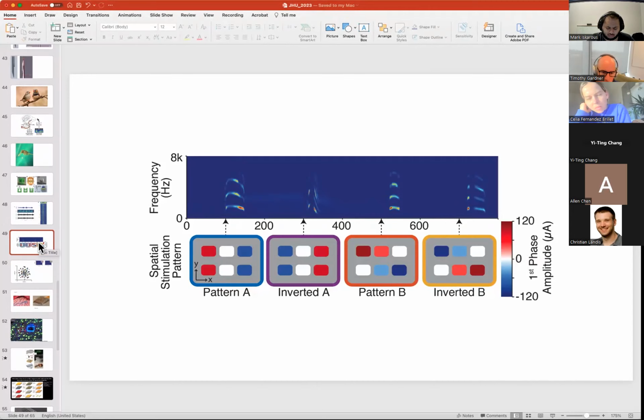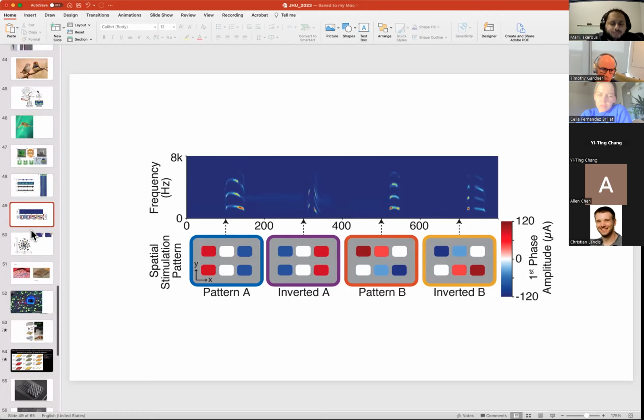variable stimulation patterns. One electrode is defined as the source and another the sink. So it's a biphasic, bipolar, or multipolar stimulation, and you can do anodal-first stimulation on one contact and cathodal-first on another, and that defines a little path for current steering between those electrode contacts and gives you pretty good spatial control, apparently, over the activity within that nerve, at least to the degree that we need to drive different vocalizations in the songbird.